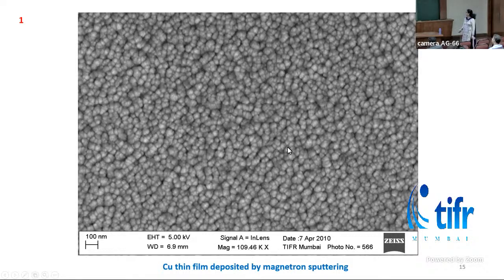So in these thin films, we check for the grain size, we check for the homogeneity of the grains, and we check for the phase. We detect the elements present in the film, and also if there are any impurities present in it. If we mount the sample in cross section mode, we can find the thickness of the sample also.